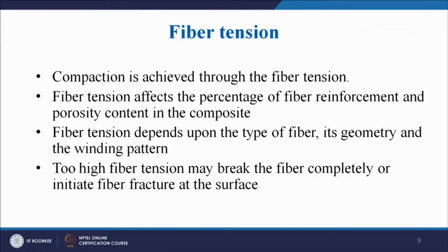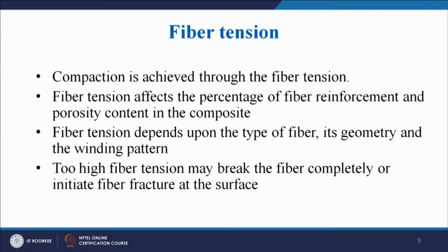Fiber tension is slightly more important. Why? Because we are not applying any external pressure on the composite product being processed here. So the tension of the fiber will lead to the compaction of the composite product, and compaction is achieved through the fiber tension. Fiber tension affects the percentage of fiber reinforcement and porosity content in the composite.